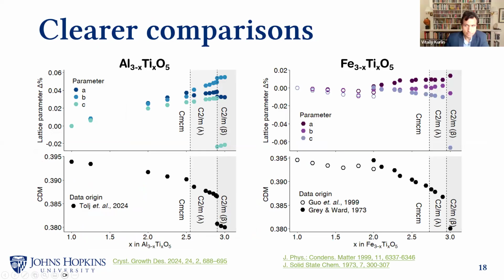One thing to mention is also in the second example, very often when you're looking at large families of material, there are multiple sources which can vary by a lot of things, the way they are refined, the time when they were discovered, which can change the lattice parameters themselves, but CDM does allow you to better combine them into a single graph or single data set. But yes, the main couple of points from the left files are from my paper, newly synthesized materials. However, the higher titanium content is from the paper which was cited in our article. Okay, thank you.